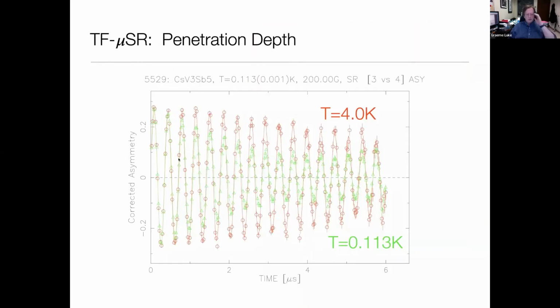So the first thing we did in this material is we did measurements in a transverse magnetic field to measure the relaxation rate. Here we are above TC, you see very weak relaxation. This would just be due to the nuclear dipole moments of the material in the system. And then as we go into the superconducting state, we set up a vortex lattice, which makes the field distribution less homogeneous. And so we have a damping of the relaxation. So we fit this to extract the damping rate.